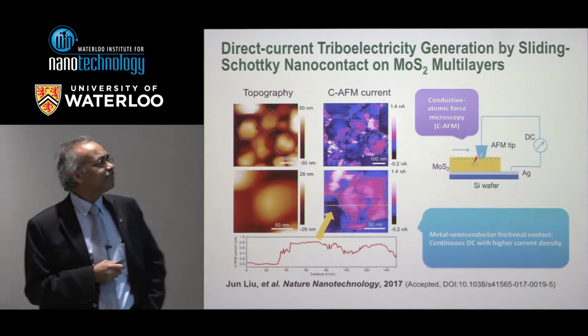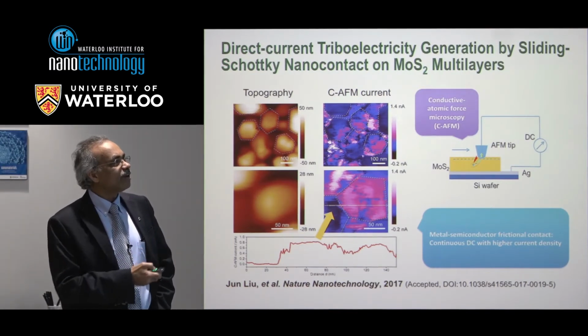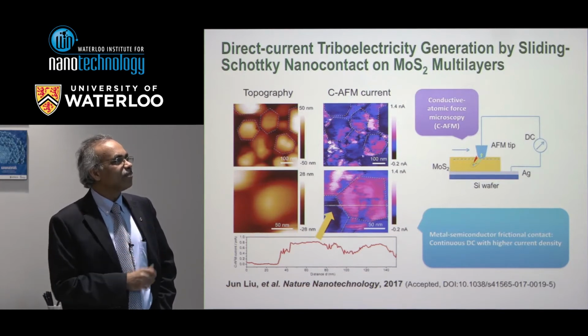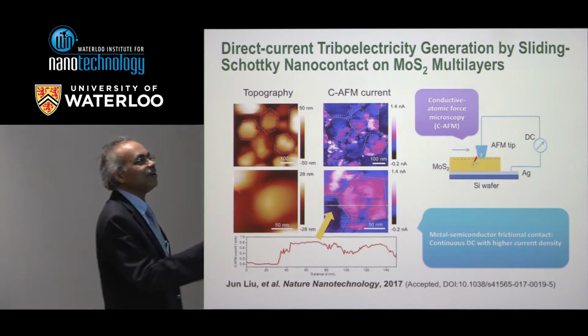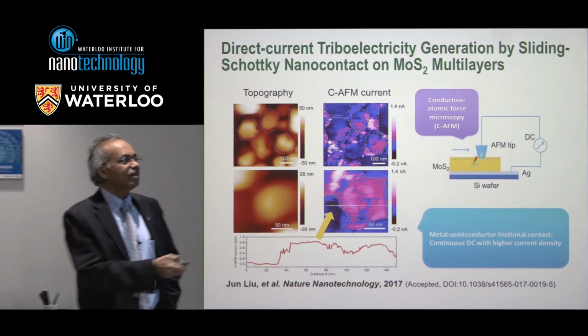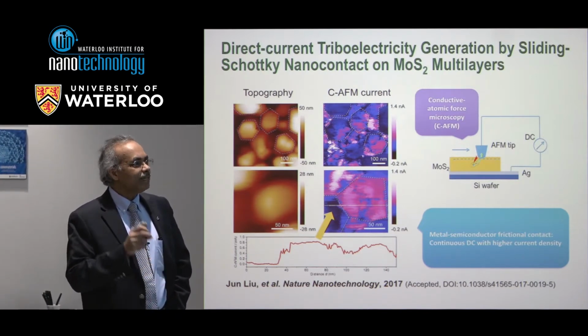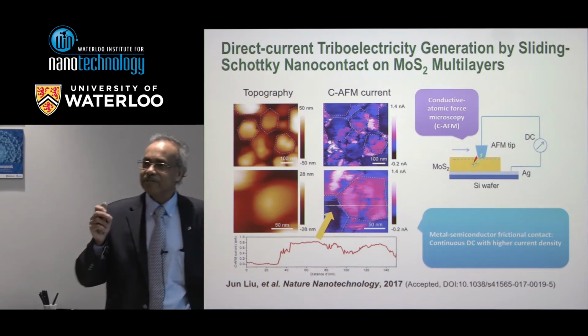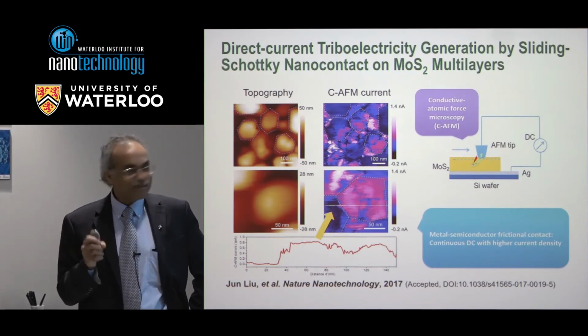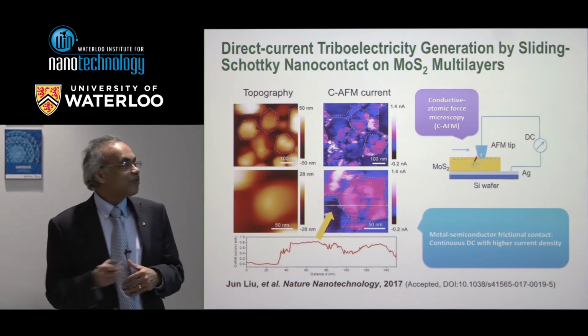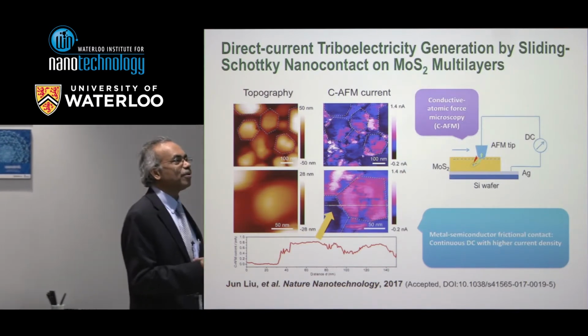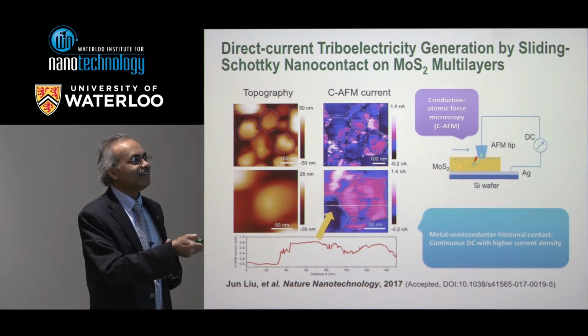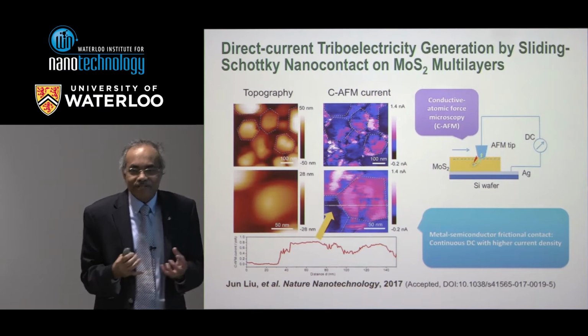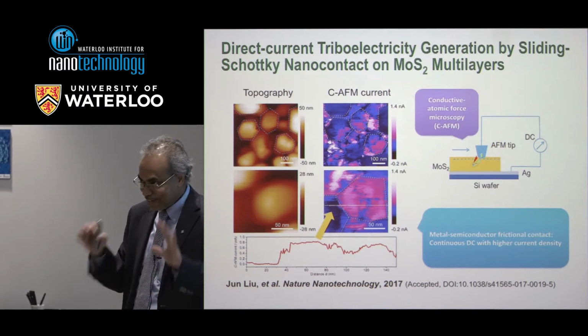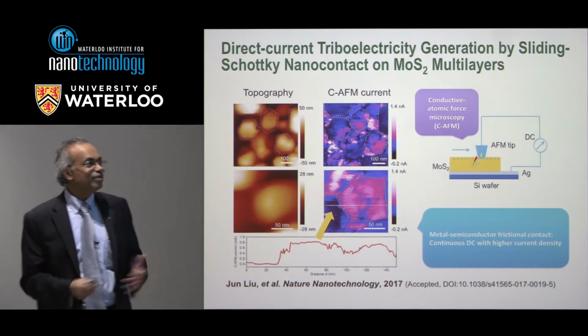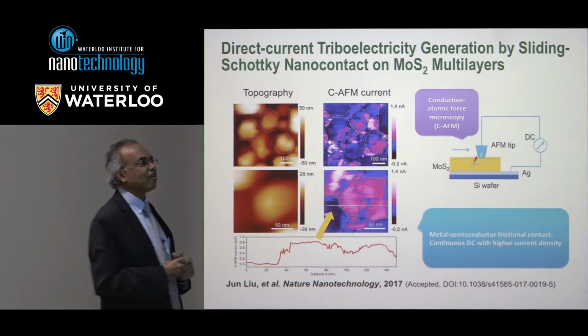So this is what we came up with. We took molybdenum disulfide, made a PLD, pulsed laser deposition, on the surface of a material like silver grown on silicon. And basically, if you rub it with the AFM tip, it creates lots of current. So there's lots of interesting physics here. What ZL Wang and the triboelectric people are doing, they are not using a conductor here, they are using a polymer. With polymers, you cannot get the electrons out of them. But if you can move the electrons back and forth, you should be able to get lots of current.